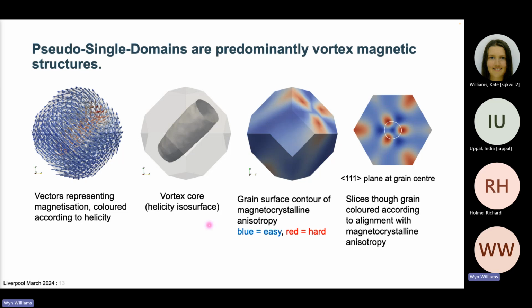So these pseudo-single-domain grains, of course, are completely obvious to me now because I've looked at them too long, but they are vortex structures. So vortex structures are an example of a pseudo-single-domain grain. It isn't exclusive with any other types of structures. And of course, in very high anisotropy materials, you probably wouldn't get vortex structures. But in magnetite, for sure, titanomagnetites, these vortex structures dominate the pseudo-single-domain grain size range.